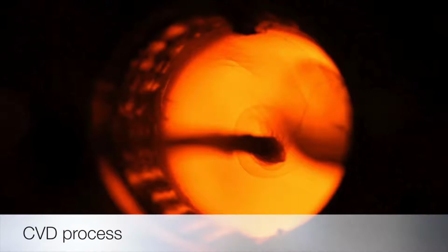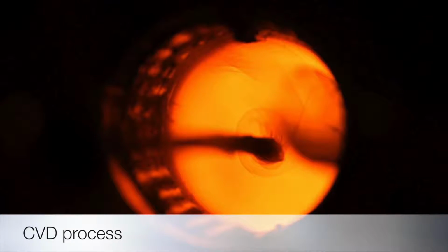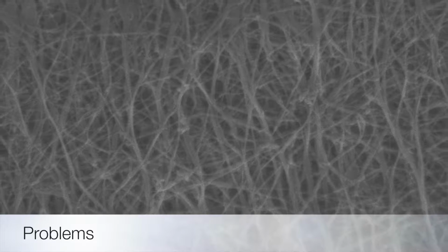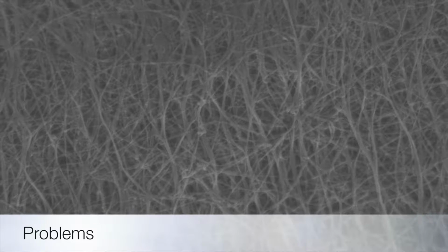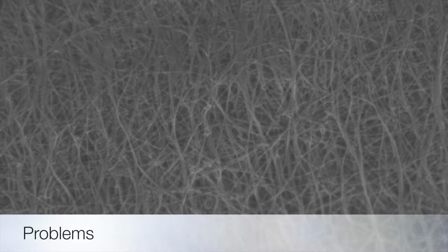This cloud is then spun out with a rotating spindle to form different variations of the material, such as films and fiber. Problems arise in great part from the material, as it has impurities, and up to today there is no way of controlling the chirality of the carbon nanotubes. So you'll always end up with a mixture of tubes with different properties.